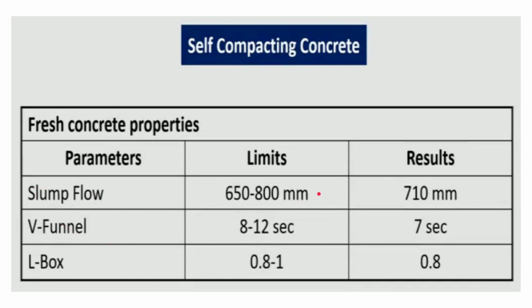Okay, so this table lists the measured values, between which standard values the parameters of self compacting concrete should come, in terms of fresh concrete properties. So the slump flow should be between 650 to 800 millimeter, and results have found that it comes around 710 mm.